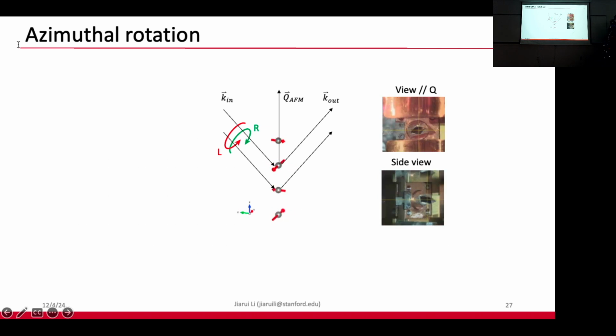To get further information on these magnetic structures, we use an additional technique called azimuthal rotation. During the diffraction, we have the K in and K out, and this satisfies the Bragg condition. And this azimuthal rotation is rotating the material along this momentum transfer, so that the Bragg condition is always satisfied. And here is a photo from the experiments to show you how this is performed. Since the Bragg condition is always satisfied, we are actually modulating the relative orientation of the magnetic spins, or it could be orbitals as well, relative to the photon polarizations.